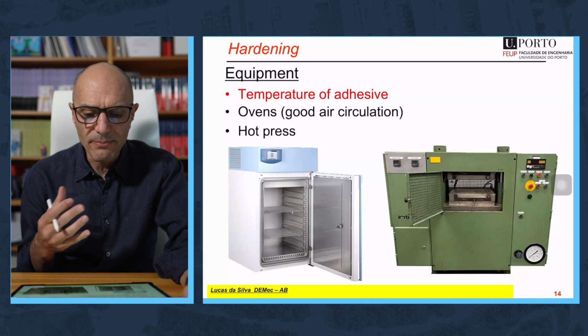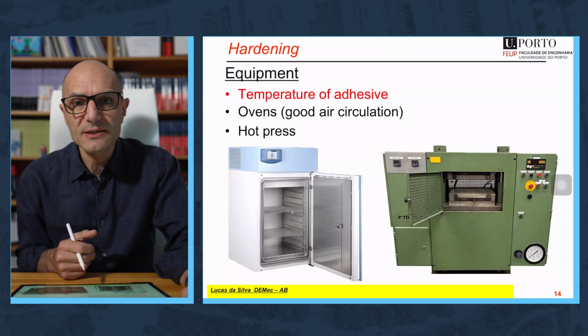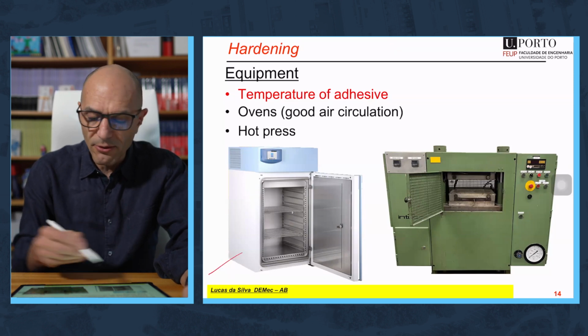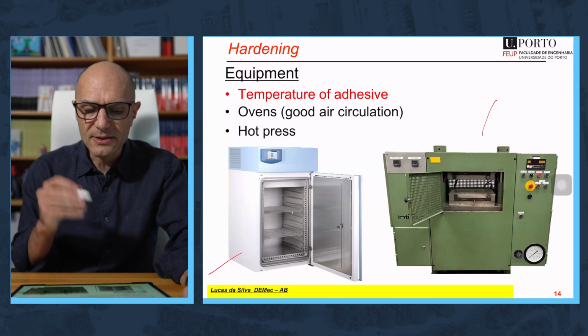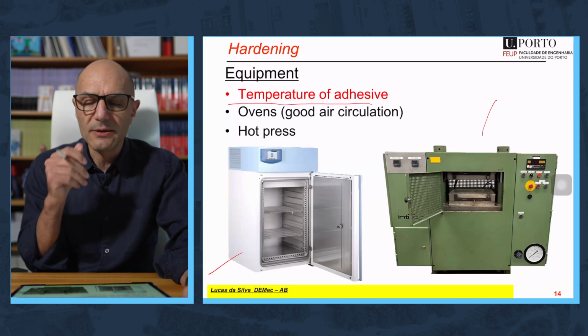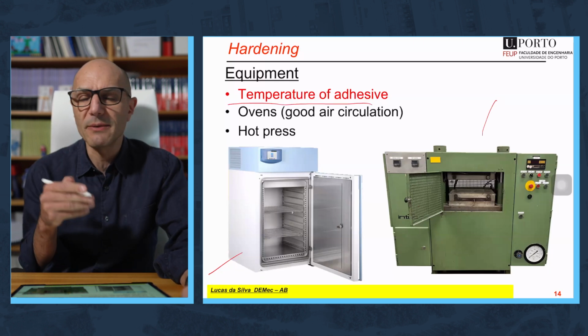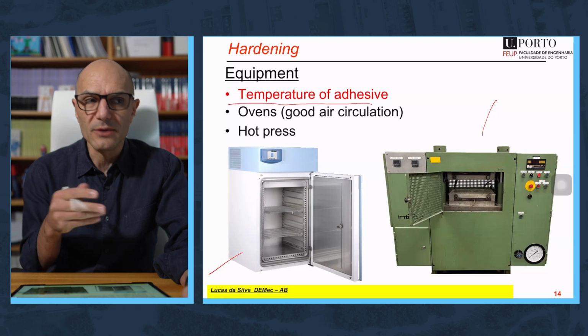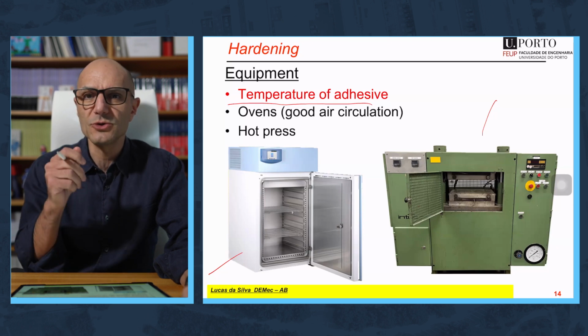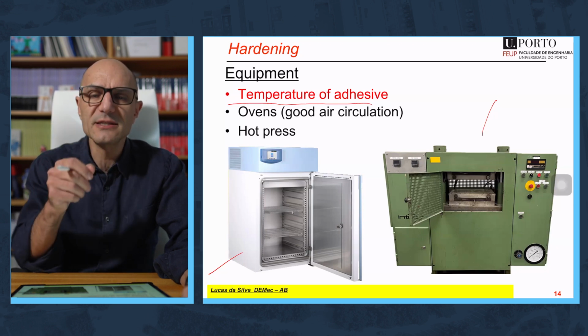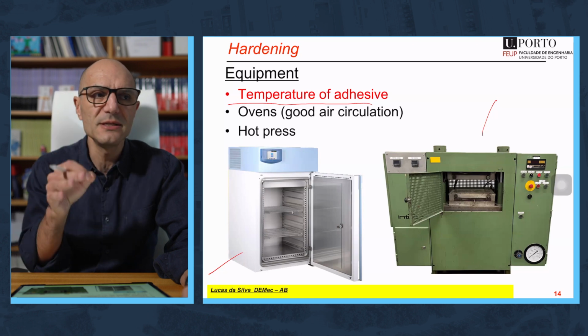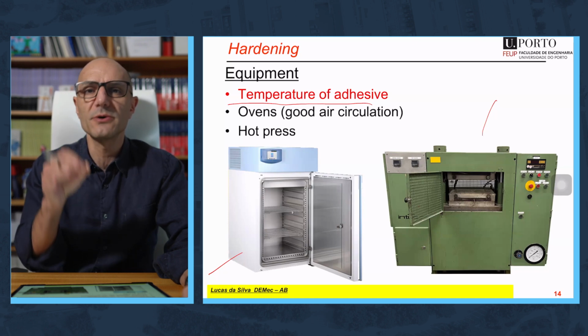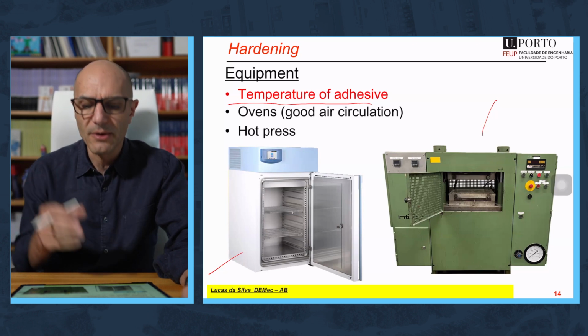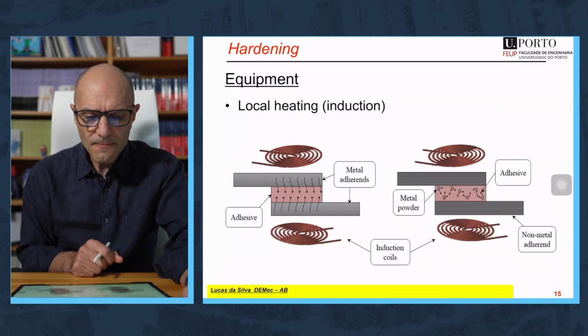About the temperature, there are several devices to apply the temperature. There are ovens, there is hot press, but it's very important to control the temperature of the adhesive. Don't use the temperature of the press or the oven. You will have wrong results. You should have a thermocouple next to the adhesive, and only when the adhesive reaches the cure temperature, then you start to count the time of curing.